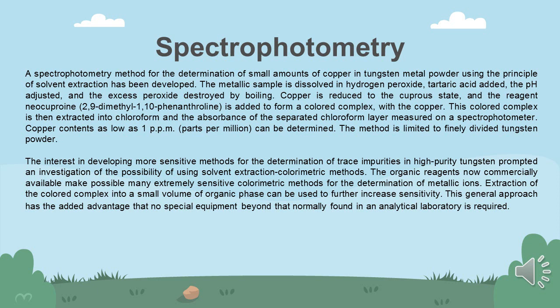Copper is reduced to the cuprous state, and the reagent neocuproine, 2,9-dimethyl-1,10-phenanthroline, is added to form a colored complex with the copper. This colored complex is extracted into chloroform and the absorbance of the separated chloroform layer measured in the spectrophotometer. Copper contents as low as 1 ppm (parts per million) can be determined. The method is limited to finely divided tungsten powder.